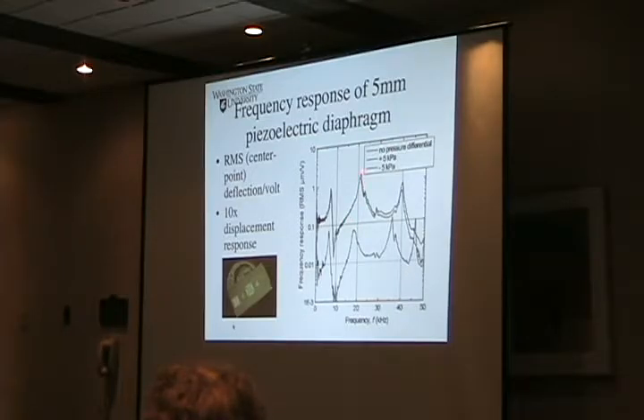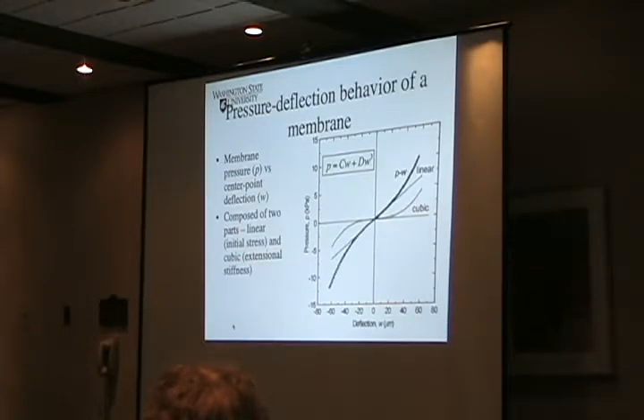So we can pressurize the membrane back and forth. We get changes in frequency response. That's nice. And so what we do is we say, well, we have a linear component in pressure deflection and we have a cubic component. The linear term is going to be solely related to the residual stress, and the cubic term will be related to the modulus.